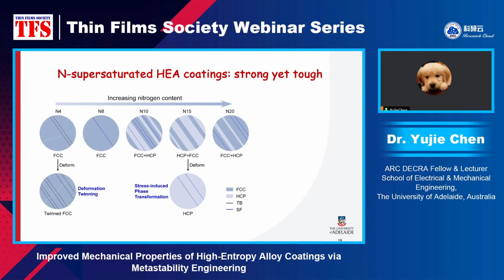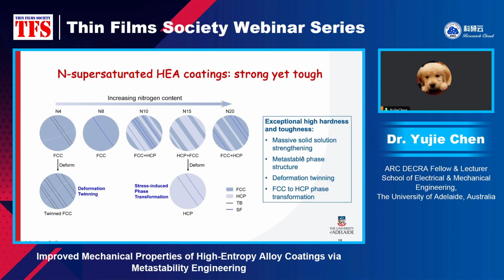Now we understand that nitrogen has strong effect on phase stability and the deformation mechanism. It's possible to apply the metastability engineering strategy in high entropy alloy coatings through adding high content of nitrogen. It can be nitrogen or it can also be carbon or oxygen. And the massive solid solution stemming from the high nitrogen intake provides high hardness. More importantly, even at high nitrogen content, they still have the ability to deform plastically like a pure metallic material. They can show deformation twinning and the phase transformation.